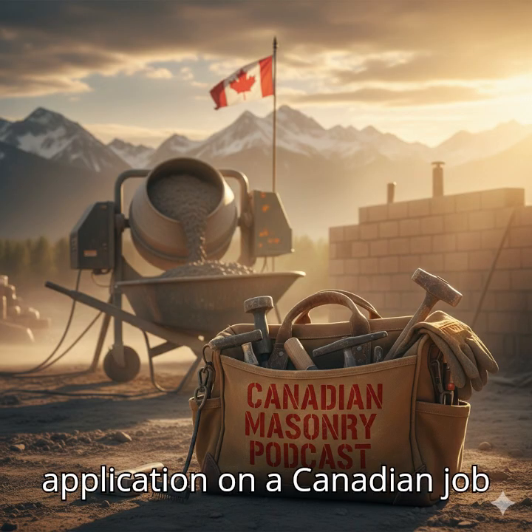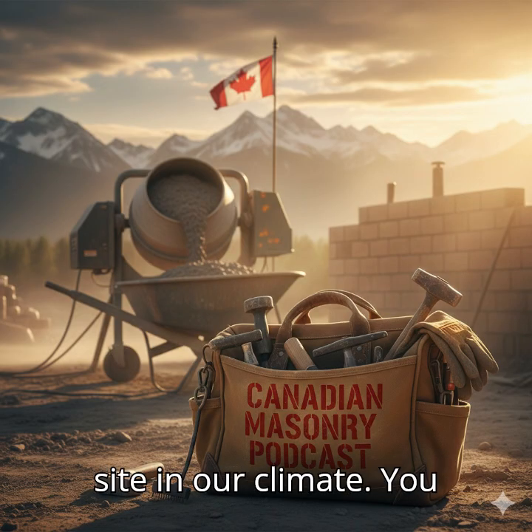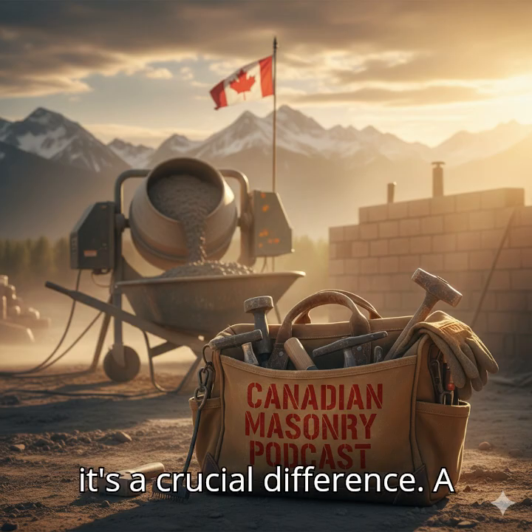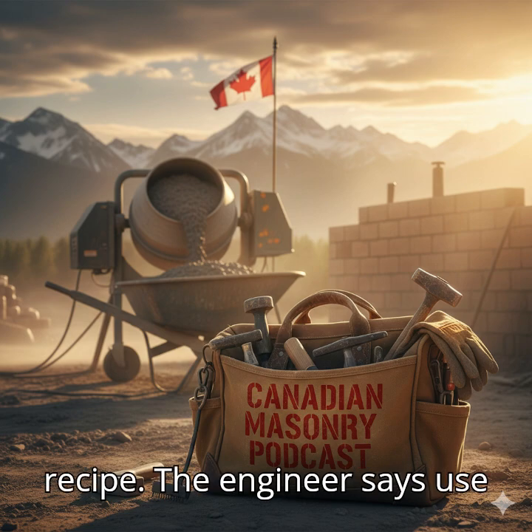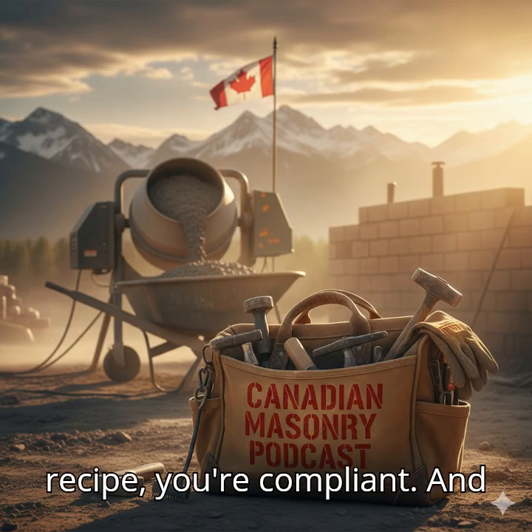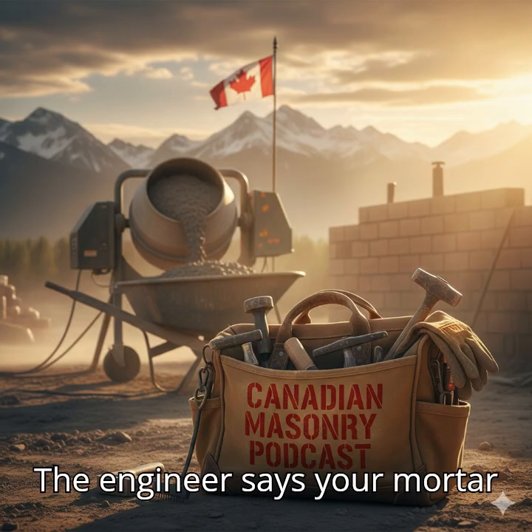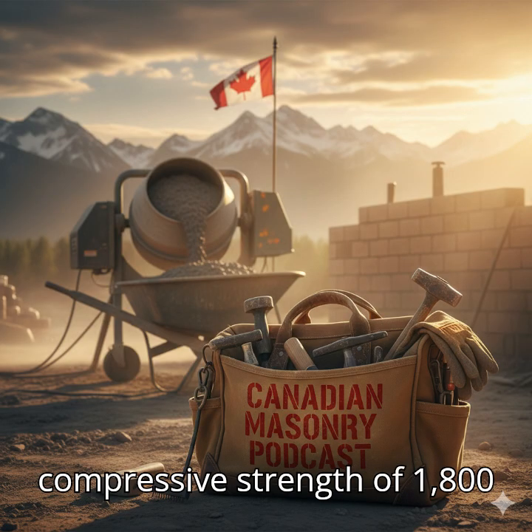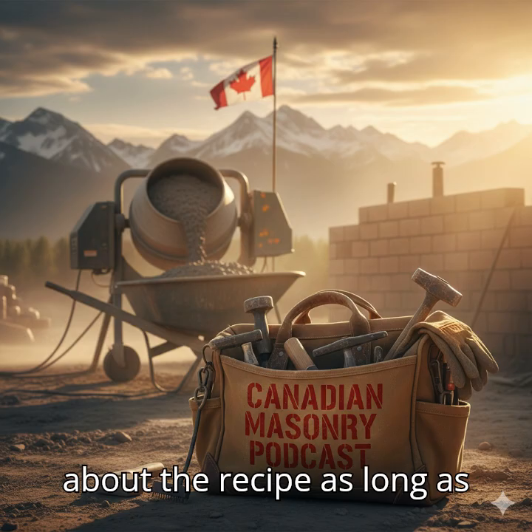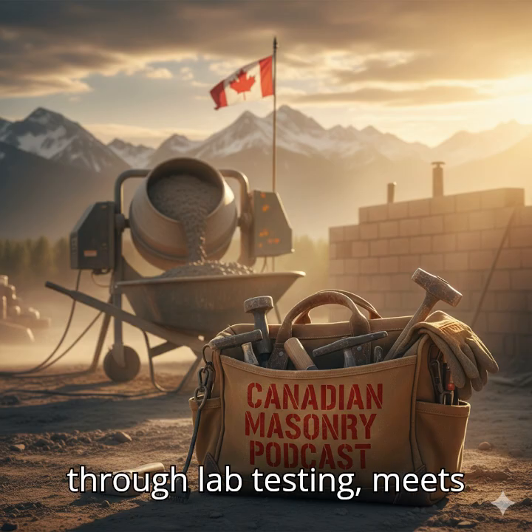Okay, that brings us to the practical side of things, the real-world application on a Canadian job site in our climate. You mentioned that specs are written as either proportion or property specs. Right, and it's a crucial difference. A proportion spec is the recipe. The engineer says use a 1:1:6 mix for type N, and as long as you follow that recipe, you're compliant. And a property spec? A property spec is about performance. The engineer says your mortar must achieve a minimum compressive strength of 1,800 psi. They don't care as much about the recipe as long as the final product, proven through lab testing, meets that structural demand. And that's more common for highly engineered structures.